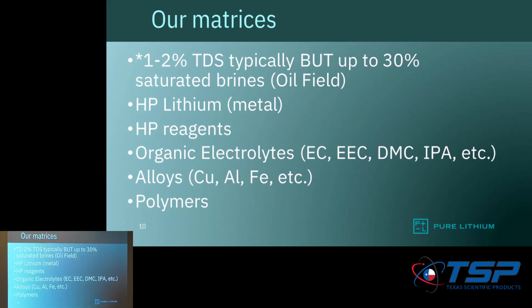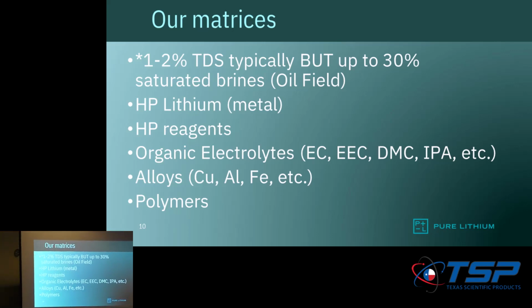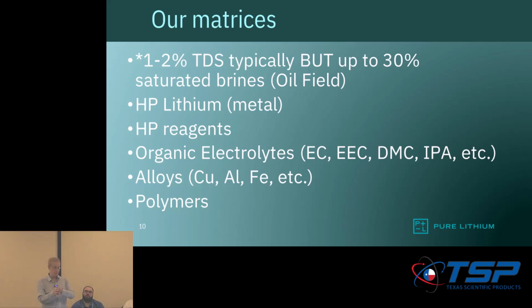So you say, how do you make a battery out of an oil field brine? Well, you put this polymer membrane in the middle. On one side, you fill it with the electrolyte and a certain amount of lithium already in there, and you put the cathode in there. On the other side, you put your salt water, okay, your oil field brine. And the lithium will be deposited electrochemically to create the battery. So the membrane only lets the lithium through. It blocks everything else, okay? This is really the core to our technology. So as we deplete the lithium on this side, it starts to draw lithium from the salt water. And that's how this battery technology works.